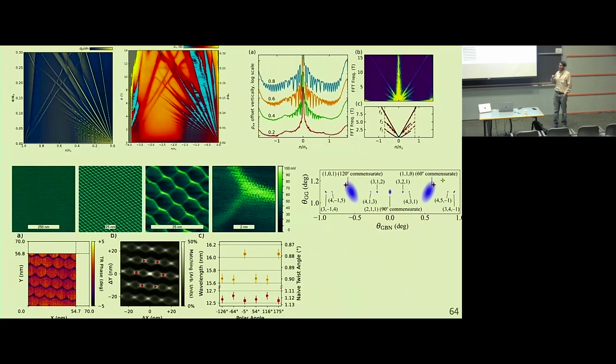How uniform is the twist? It ranges over most of the sample from 1.3 to 1.4 degrees, and in some places in the middle, it's extremely uniform between contacts, but it's not over the entire space, and nearer to the ends, it definitely diverges more.